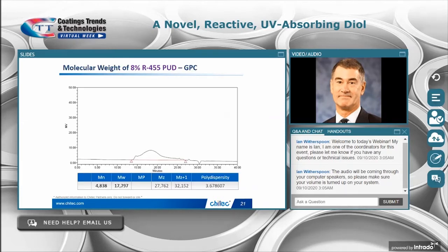Okay, and here we just are showing the molecular weight of this R455 diol inserted into the PUD at 8%, which is pretty high loading. And we see molecular weight right where it should be. So we're really very happy that it seems straightforward to incorporate the diol UVA into a PUD.